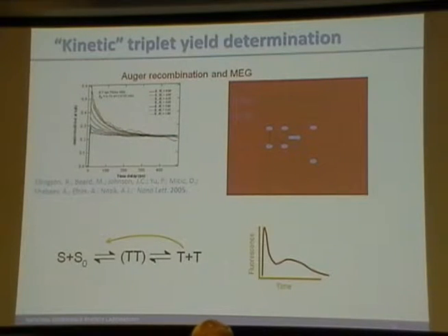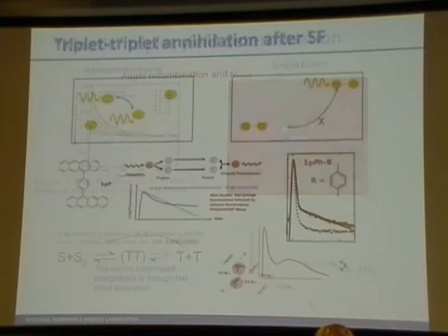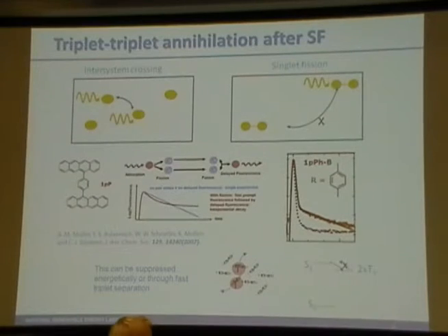And again, not all molecules even fluoresce very strongly from the singlet state, and so it wouldn't necessarily be a quantitative measure. People have tried to use this somewhat successfully in the past. This is a paper from Chris Bardeen. He used pentacene dimers. What he did is he looked at the monomer, just taking this part of the molecule, looked at its decay in solution, and got this dashed curve here, or this blue curve here.